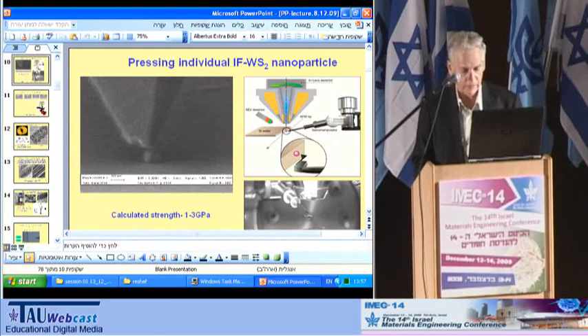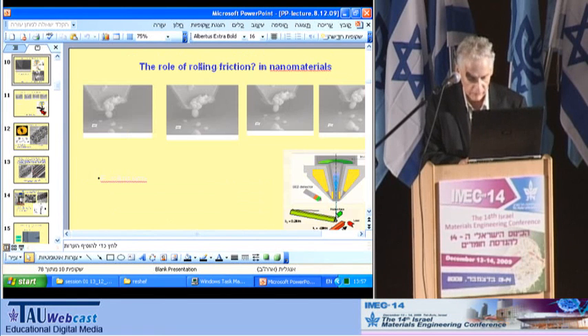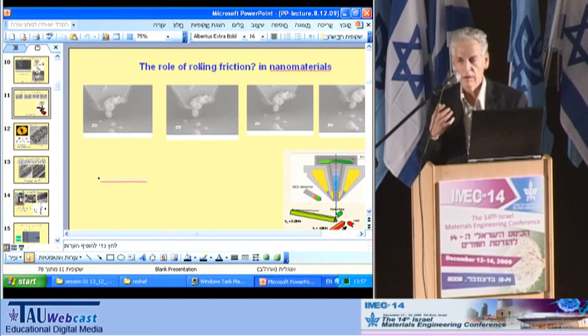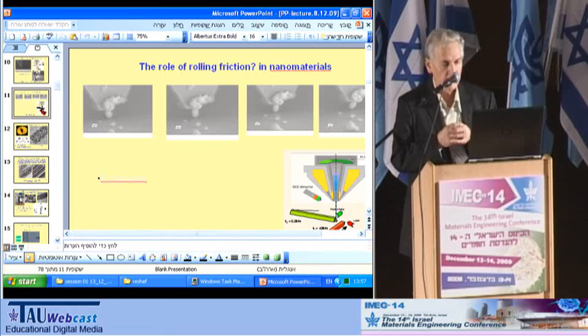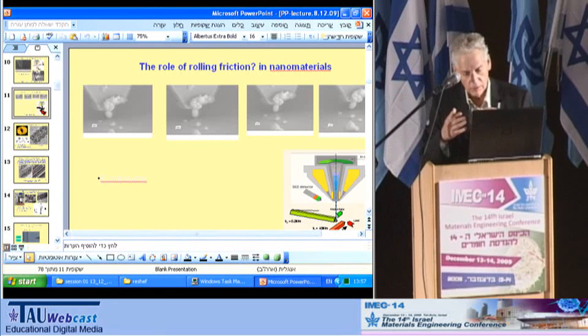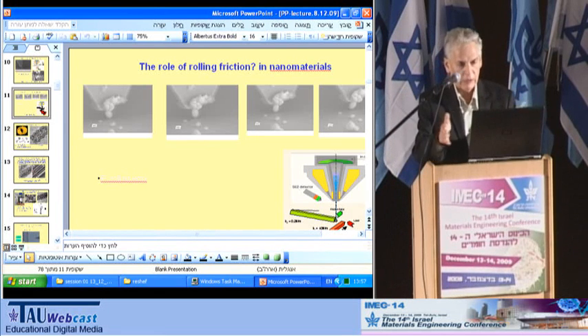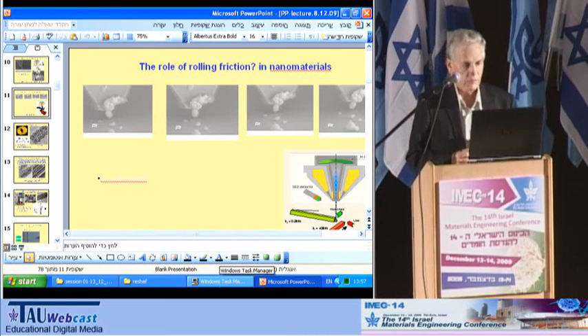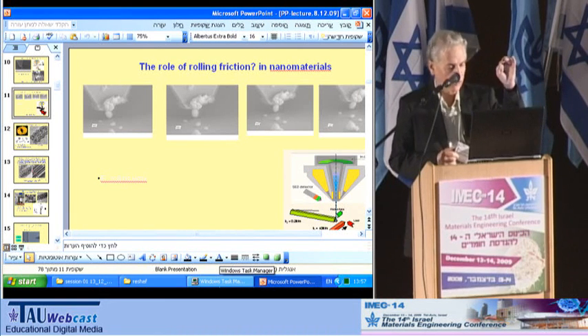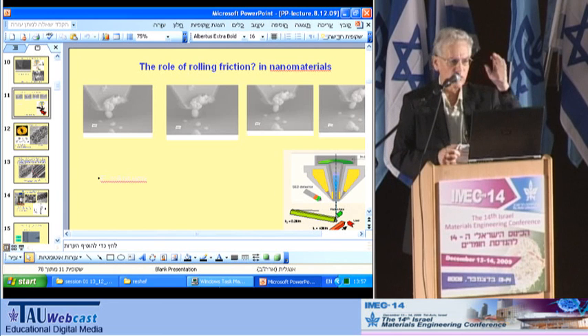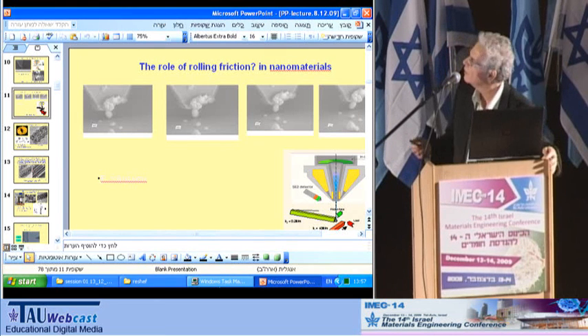This is important in terms of using them as lubricant, because now we start to understand the properties of these nanoparticles individually. And of course, when you come to a group of nanoparticles on the surface, they are entrapped, and therefore their mechanical behavior may be different, but nevertheless, it still shows that they can behave as very good nanoparticles which withstand a very high pressure and load.